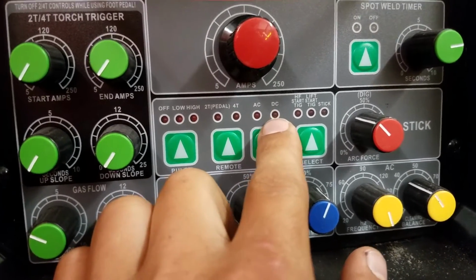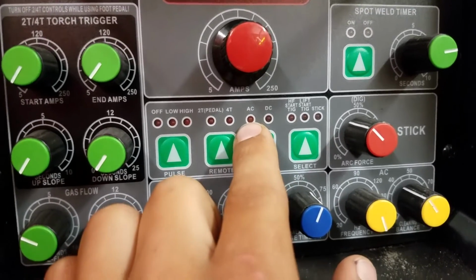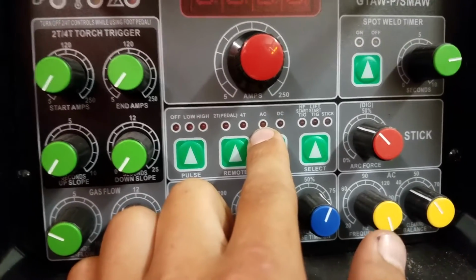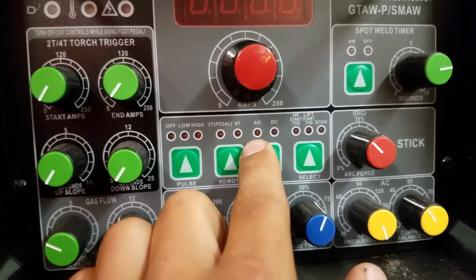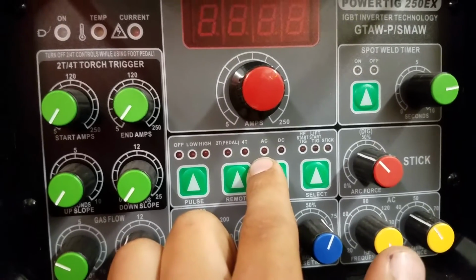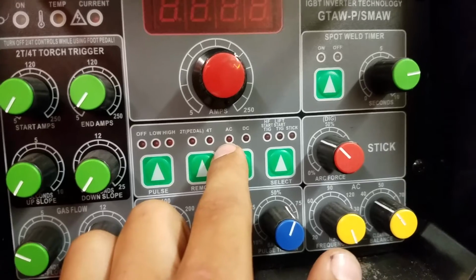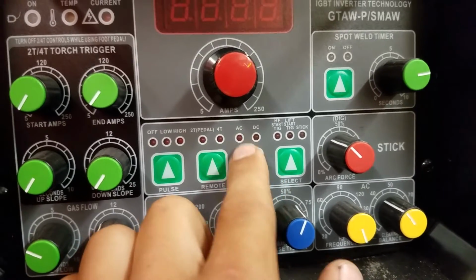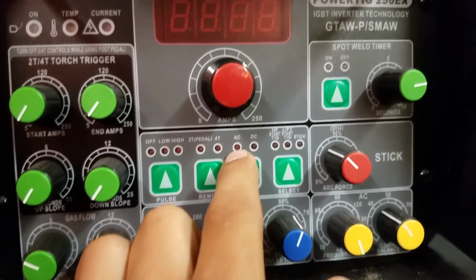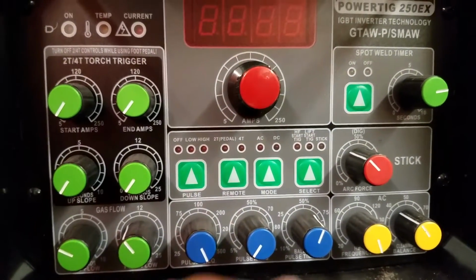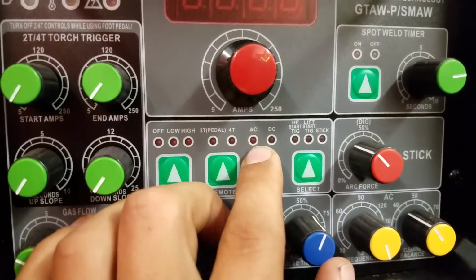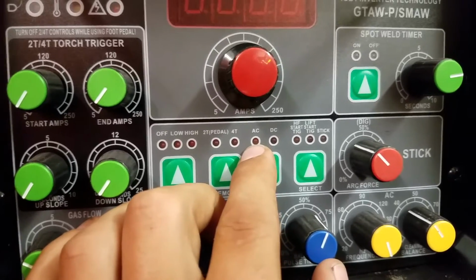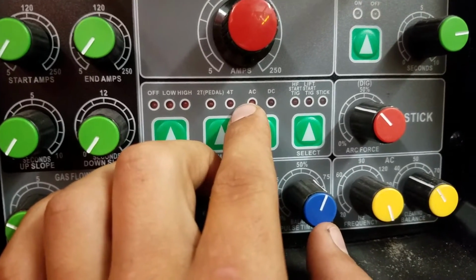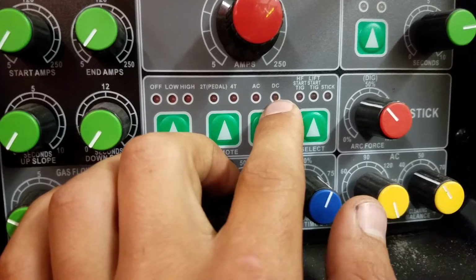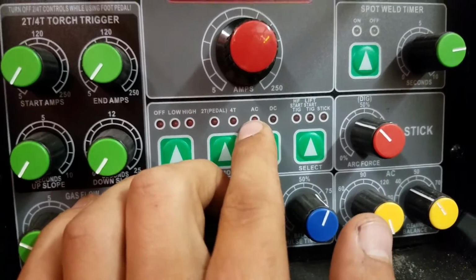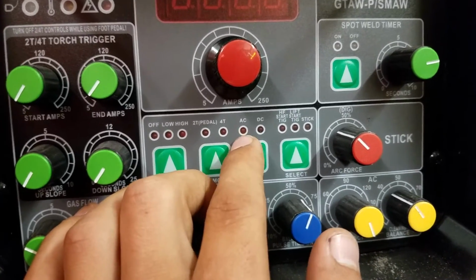But let's say that you wanted to weld aluminum, then you might put it to AC. Aluminum forms an oxide layer very quickly, called aluminum oxide, and the only way to break that up is by using a quick pulse of DC electrode positive. And so AC switches back and forth very quickly between DC electrode negative and electrode positive, which is called a cleaning effect. So when it's in electrode positive mode, it's cleaning it, and when it's electrode negative, the normal DC one, then it's welding. So AC is for aluminum and lets you go back and forth.